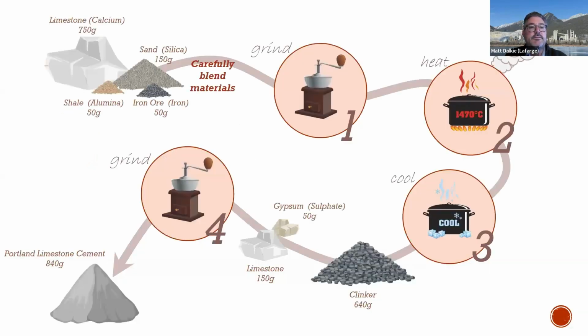So this is the cement manufacturing process. We start off with all of these raw materials up here. So this is 1 kg of raw material. We grind those down into a fine powder. We heat those up in the kiln and preheater tower up to around 1400 or 1500 degrees Celsius, depending on the chemistry. And that's where most of the CO2 associated with cement manufacturing is released.